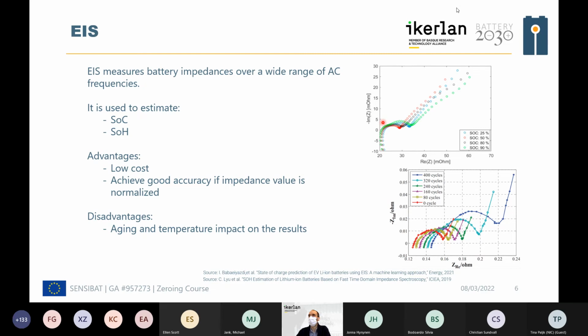You can see that at some points we have almost the same impedance at different SOC values. In addition, the impedance change is more sensitive to temperature change than to the charge change, and therefore compensation must be addressed if we want to factor out this temperature influence from the estimation.